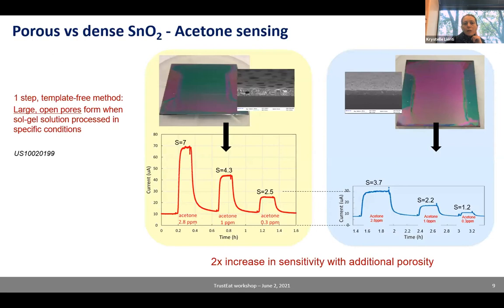Then I'm showing another example here where we prepared tin oxide with different surface area. So we started with the same Sol-Gel formulation and we just processed it in different conditions. And by doing so, we achieved a film that was completely dense, or a film that had these macro pores forming throughout the film without even using any templating agent or anything, just by processing it in different conditions. And so what's nice is that because they come from the same formulation, we know that the only difference we have is the presence of pores, so an increased surface area for this particular material here that I'm showing.